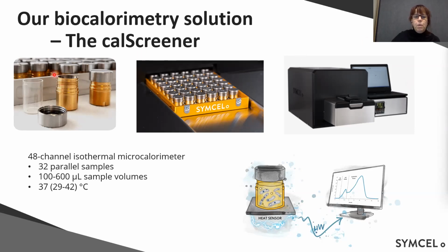You will put your sample into our sample vials. And you can also put in a small plastic insert, either a plain plastic insert, or you can have an activated plastic insert if you want cells to attach to the surface. And then you close this and you put the vials, the 48 vials or 32 ones with the sample and the references, on the plate, and this is a batch measurement, so you would push the plate in and measure all samples simultaneously